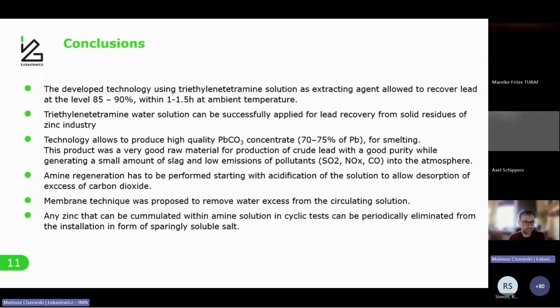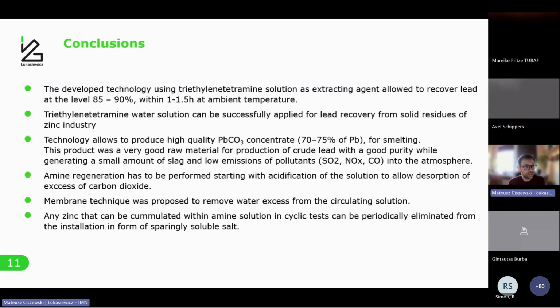This triethylene tetramine water solution can be successfully applied to other solid materials containing lead sulfate. The technology allows us to produce pure, high quality lead carbonate that can be used for smelting. It was also done in our case: our colleagues from the pyrometallurgy department smelted close to 1 ton of the lead carbonate to produce lead.